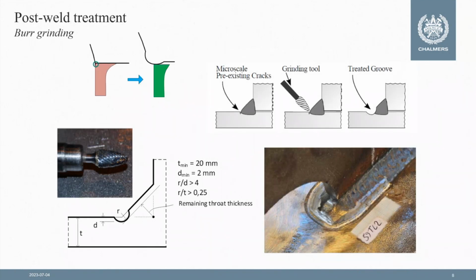One method that has traditionally been used is burr grinding at the weld toe. By grinding the weld toe, we have a better transition from the weld to the base metal. We get a lower stress concentration, and if there are any surface defects, micro cracks or undercuts at this location, then we remove these as well. That would result in enhancement of the fatigue strength, typically 1 to 2 detail categories better than the as-welded condition. So this is a method that has previously been used.